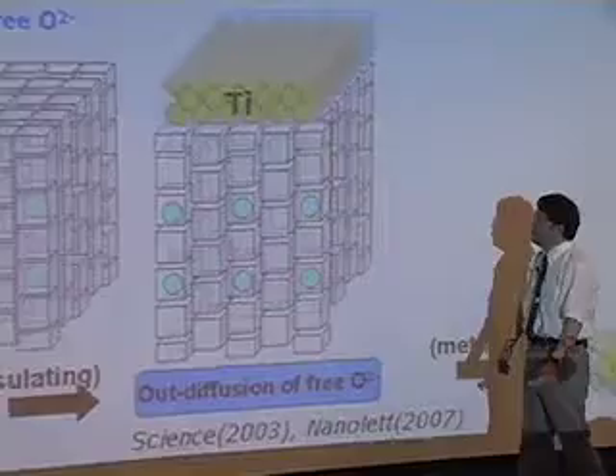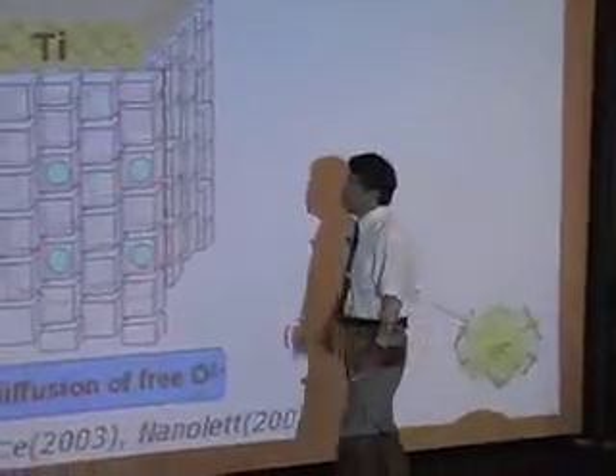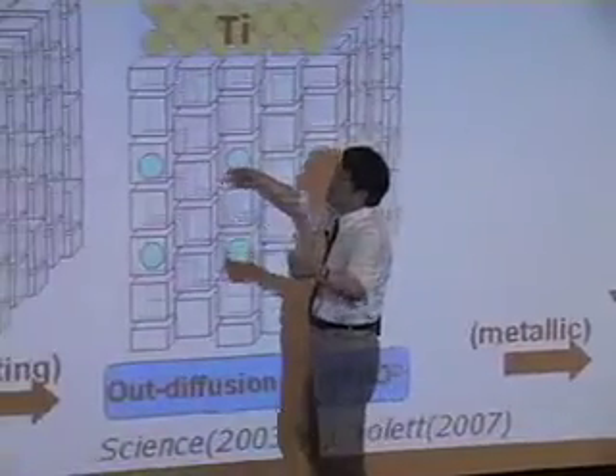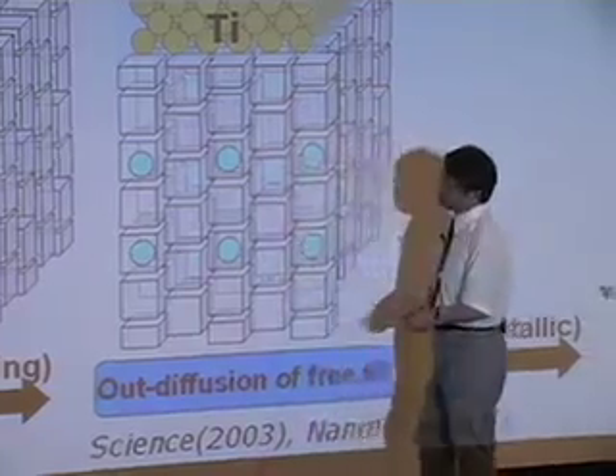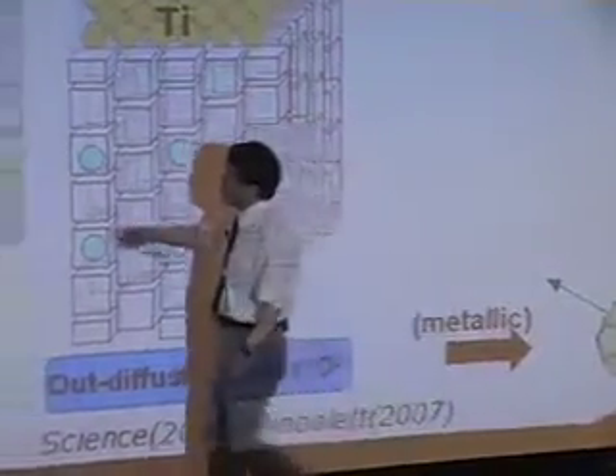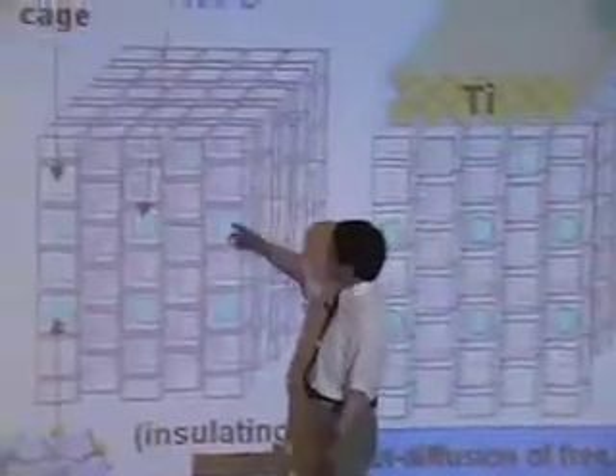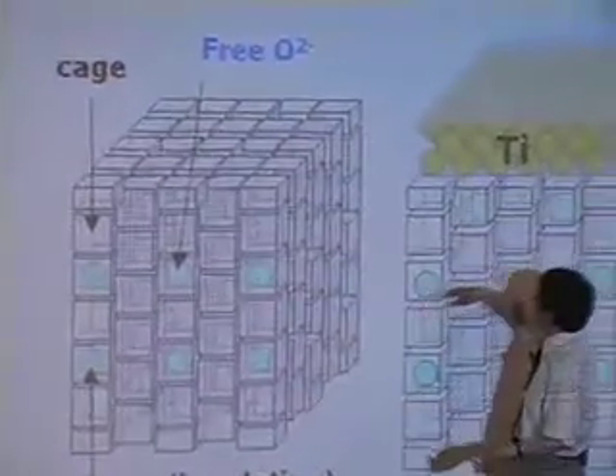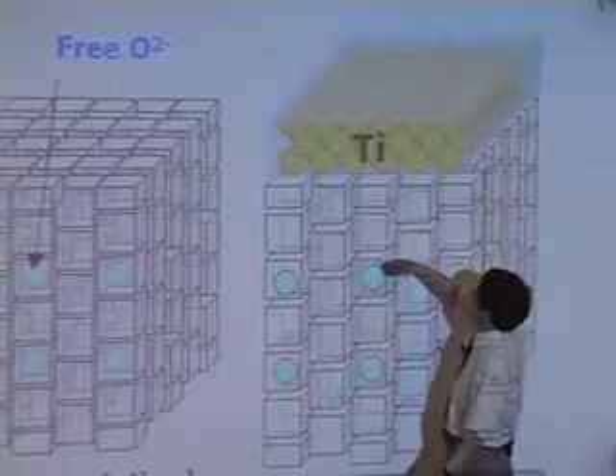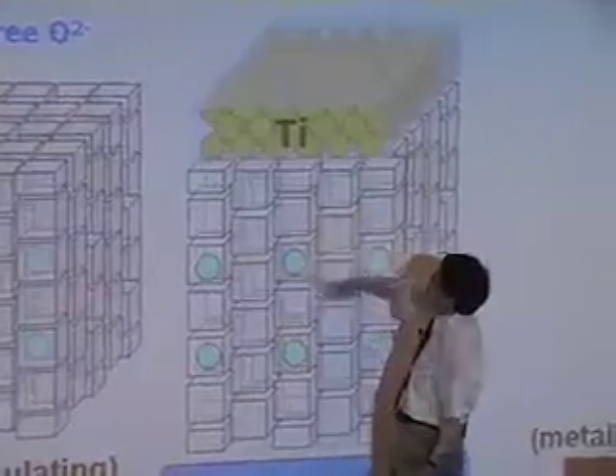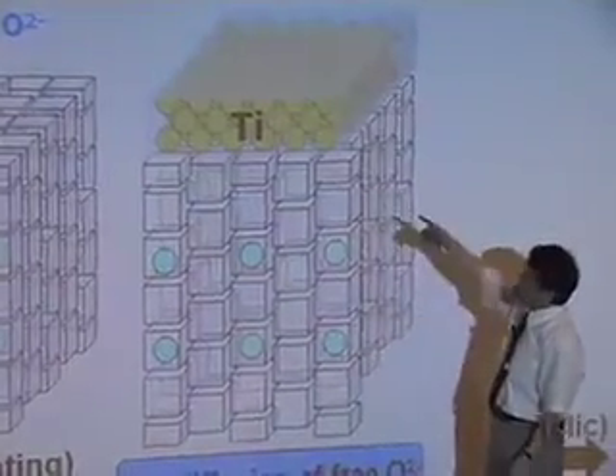We heated the sample with titanium metal shot evacuated in SiO2 glass. When the temperature goes up, the free oxygen ion moves along and diffuses away to the surface, combining with the titanium ion. The titanium-oxygen bond is pretty strong.